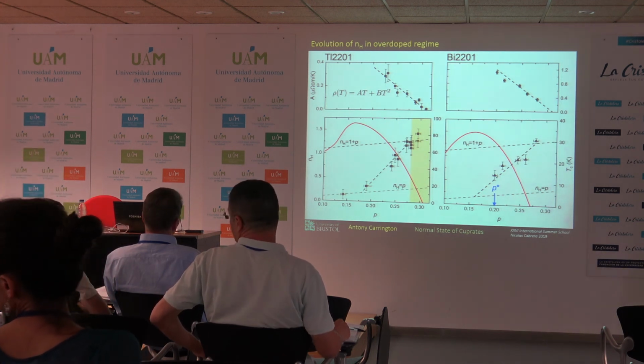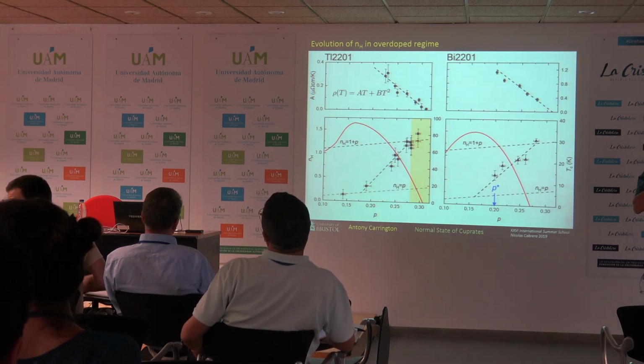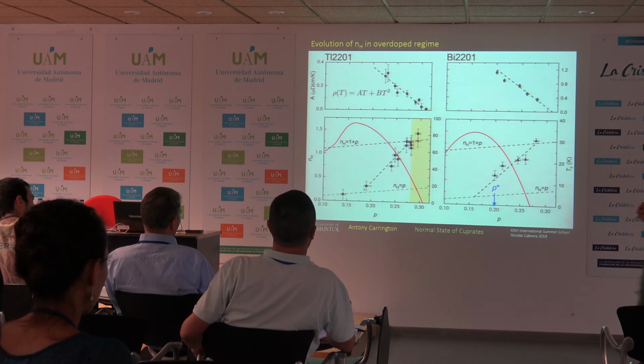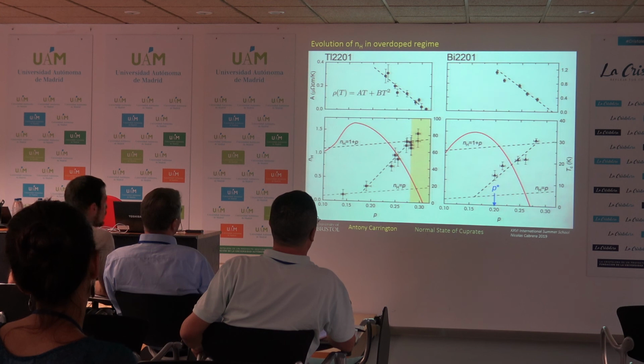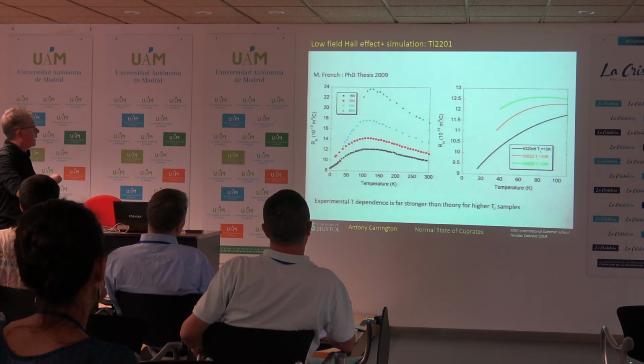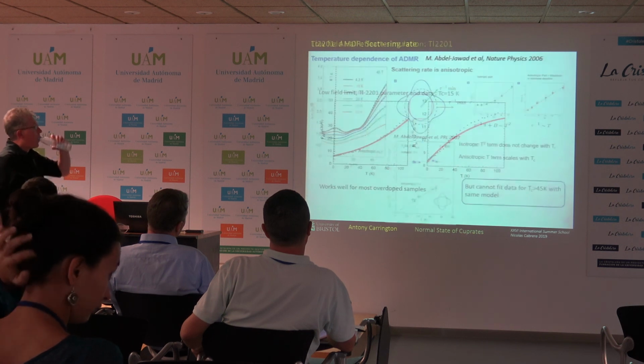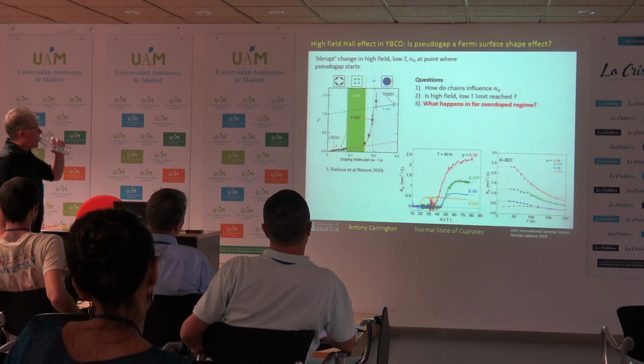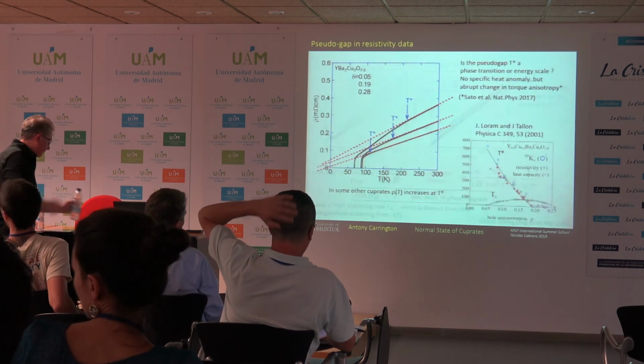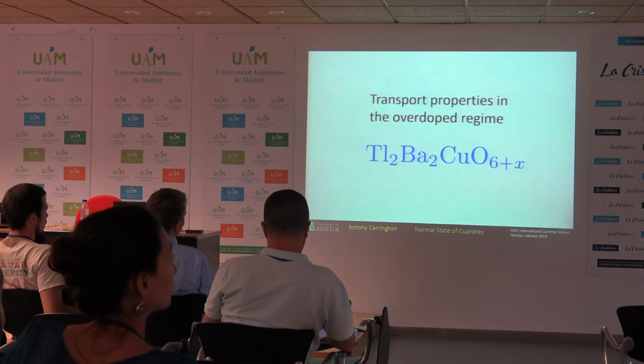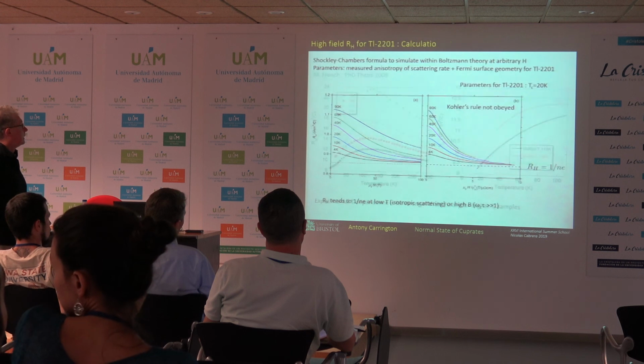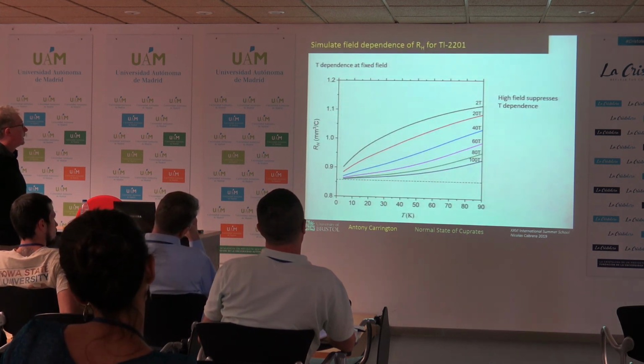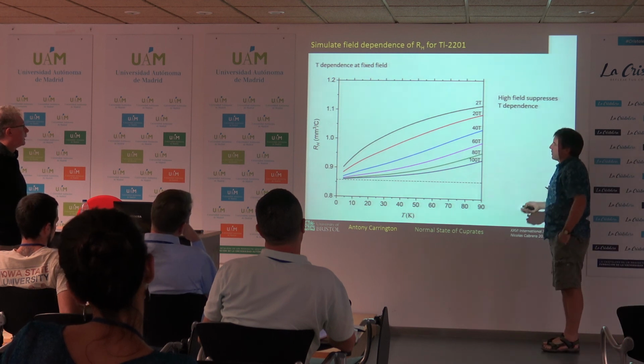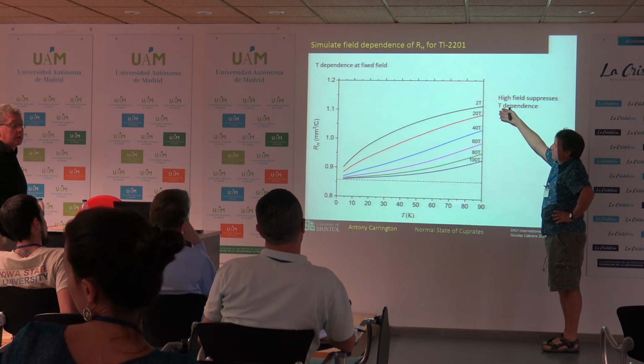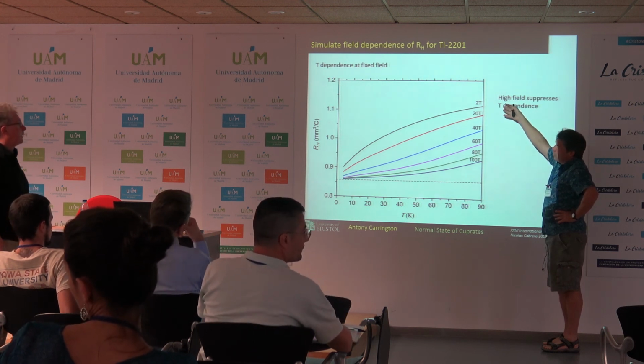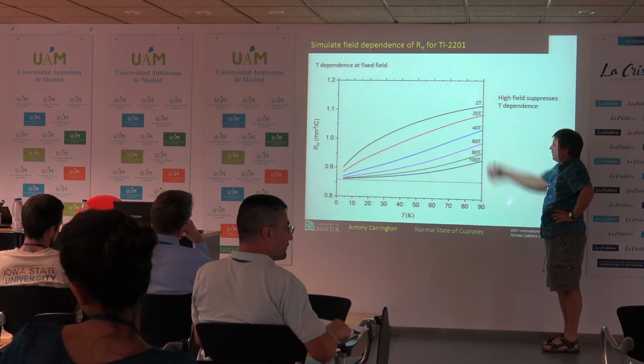So the way you extract this number is extrapolating to the highest field possible, is that right? The value of RH. Okay, I didn't quite have time to go into all of that. The slope changes in field significantly, so I wonder if the slope is telling you something. Sorry, let me just answer your question. I'll try to find the plot, which is evading me. Okay, here. So this is a simulation, actually. It's showing what the tube integral formula would tell you would happen as a function of field if you had the values of Tl-2201.